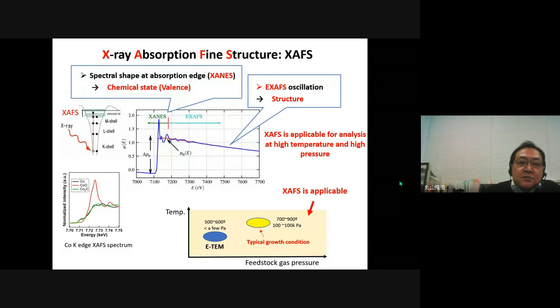So in this study, we used X-ray absorption fine structure, XAFS, measurements for in situ analysis. XAFS is an experimental technique to measure X-ray absorption spectra. The measurement of fine structure near the absorption edges, that is XANES region, provides information about the valence state of target elements. Also, analysis of the fine structure far above the absorption edge, that is EXAFS region, provides information about structure. XAFS is applicable for analysis at high temperature and high pressure. Therefore, XAFS is suitable for in situ analysis under the conventional growth condition of carbon nanotubes.